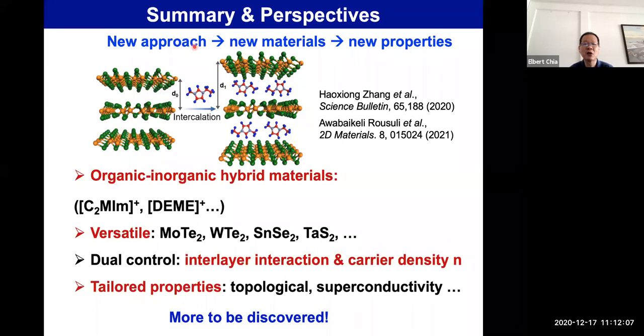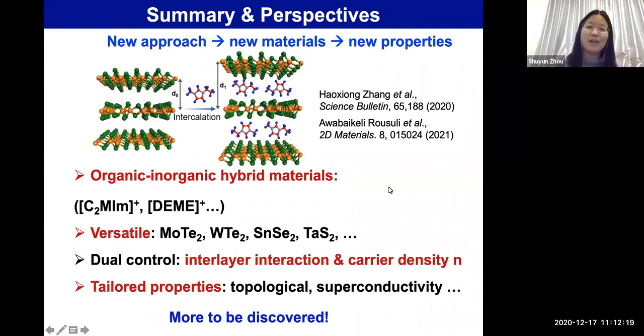Very nice talk. Thank you very much. So I want to ask whether you have measured magnetization data or specific heat data from your samples. Yeah, we did. I just replied to your email. So it's actually quite surprising that from this magnetic susceptibility, it seems that the calculated superconducting volume fraction is surprisingly low. So this filamentary superconductivity is one possibility.